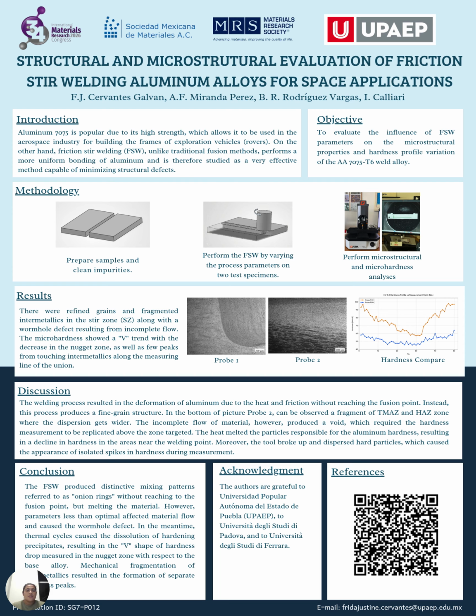The welding process resulted in the deformation of aluminum due to the heat and friction without reaching the fusion point. Instead, this process produces a fine grained structure. In the bottom of picture Probe 2 can be observed a fragment of TMAZ and HAZ zones where the dispersion gets wider. The incomplete flow of material, however, produced a void which required the hardness measurement to be replicated above the zone